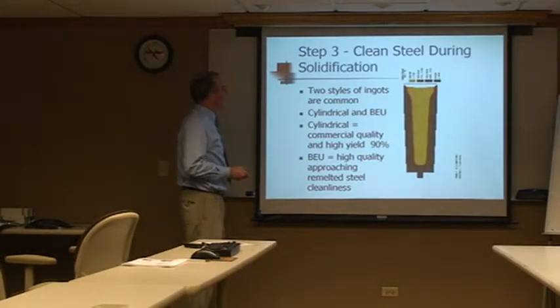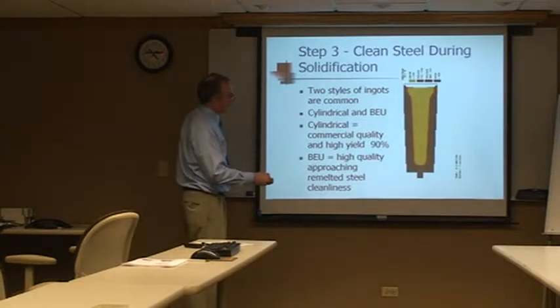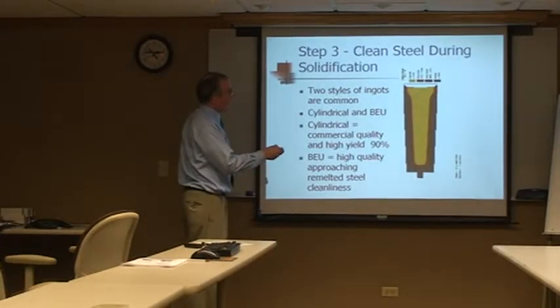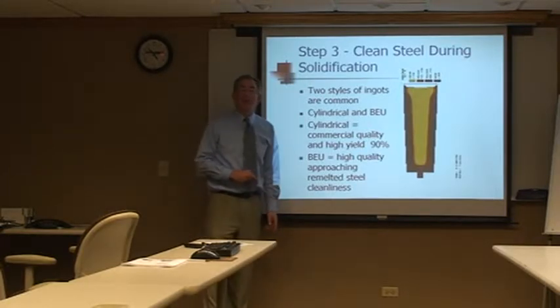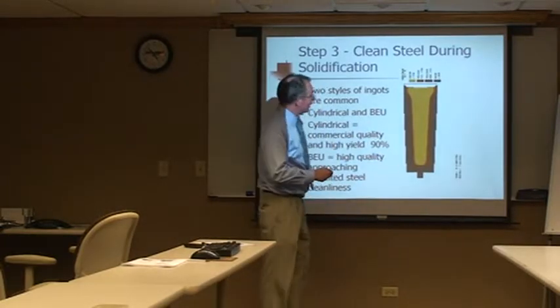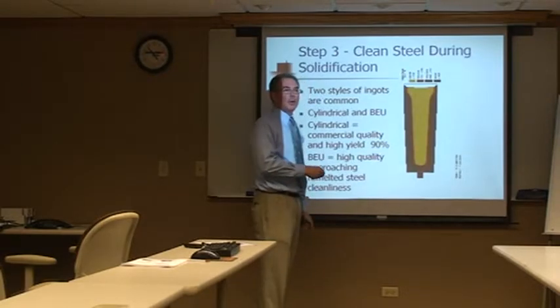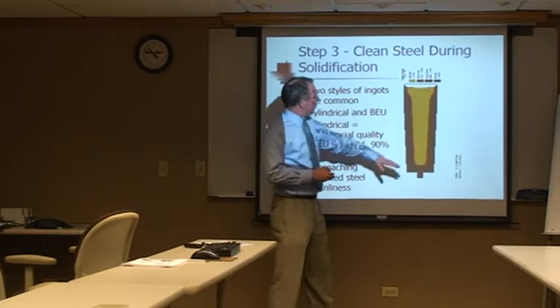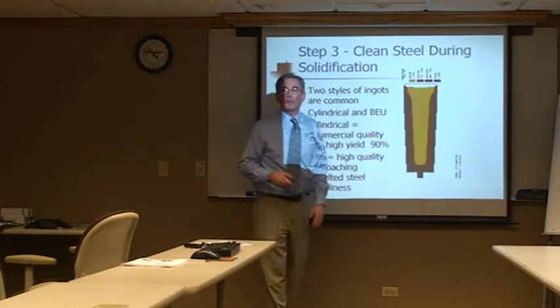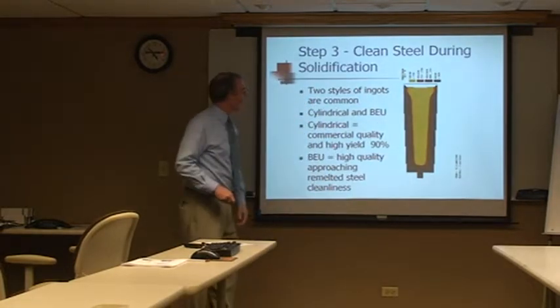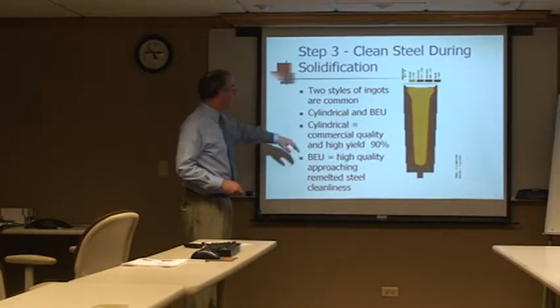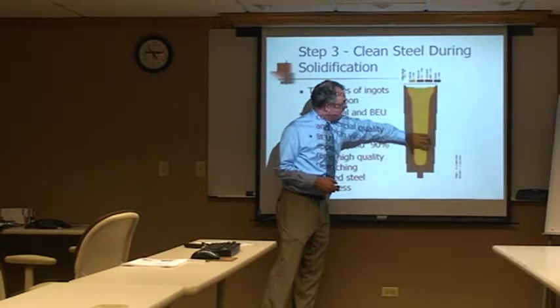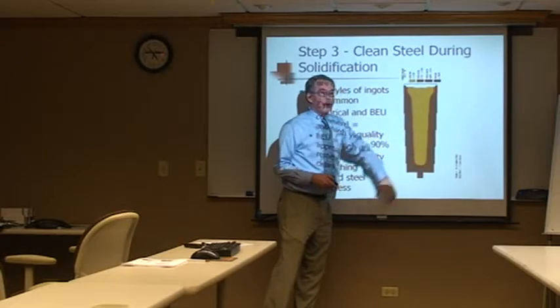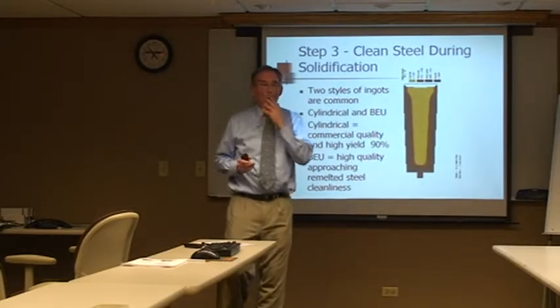Talk a little bit about mold design that we use. This is a tapered ingot. See how this solidification front is progressing? If there are any inclusions left while this is solidifying, these things are still floating. We still get extra float time here, so it still allows some chances for inclusions to float. It also, and we're going to talk about this a bit more in a second, allows the highest possible quality.